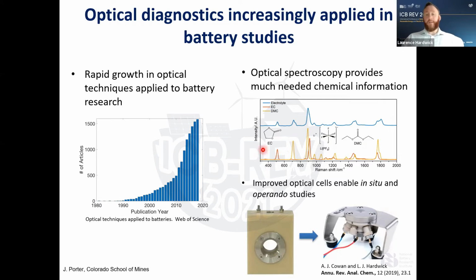If we're looking at the electrode, we can also see additional bands which may indicate different compounds forming at the electrode surface. We can see how the band shape changes, it becomes broader, or there could be a band shift, and so we can get some very subtle information about all the different areas around the electrode, the electrolyte and the interface. And this has really been enabled by developments within the lab and also commercially, there's now quite an array of different companies selling optical cells, which enable both in situ and operando studies.